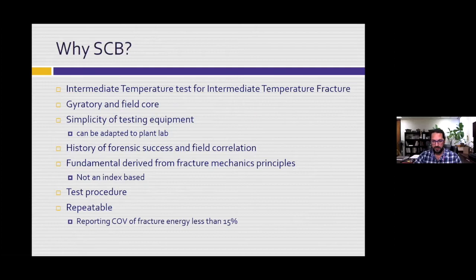And so the reasons we did it, we could use a gyratory compactor to make the specimens. We could adapt the testing equipment to a plant lab versus just our research grade equipment. And again, I can't stress enough the history of forensic success and field correlation to the test parameter we were evaluating. Okay, and we did a lot of work to get into variability and making sure the test specimens are prepared in a way that we can get good repeatability and get that confidence up.